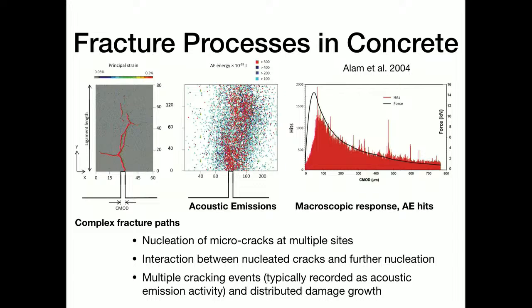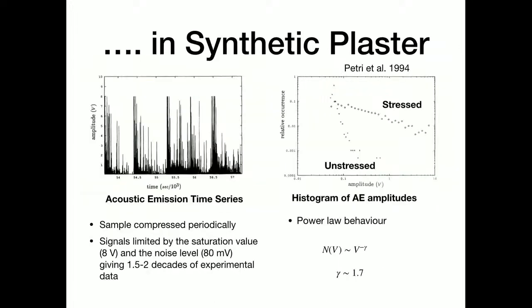Now in statistical physics, the interest has been in the nature of the distribution of the amplitude of these intermittent bursts. And here what is shown is a sample of synthetic plaster. It is compressed periodically to simulate the effect of aftershocks, and what is looked at is the distribution of the amplitude of these events, and it is found to be a power law with an exponent of 1.7.